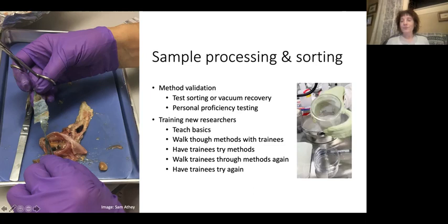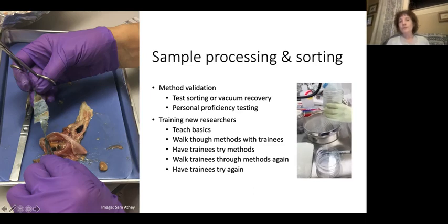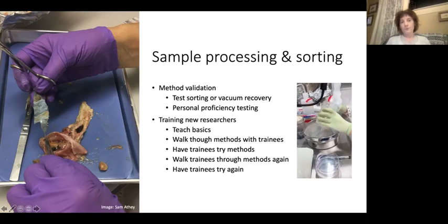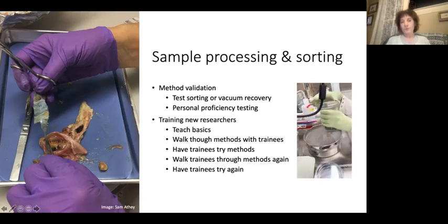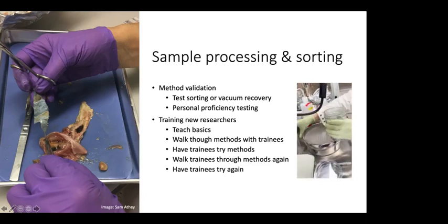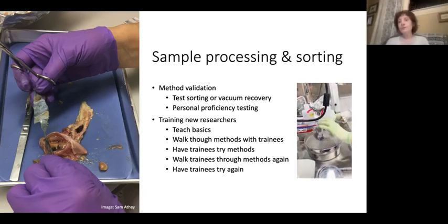So here I'm working inside one of our laminar flow hoods with a HEPA filter that helps prevent much of the plastic contamination in the air from reaching the samples. I am processing spraints or scats that were collected from wild sea otters in Alaska. I have dried the spraints, digested organic material with potassium hydroxide, and performed a density separation to try and remove the potential plastics from the shells and sediment.